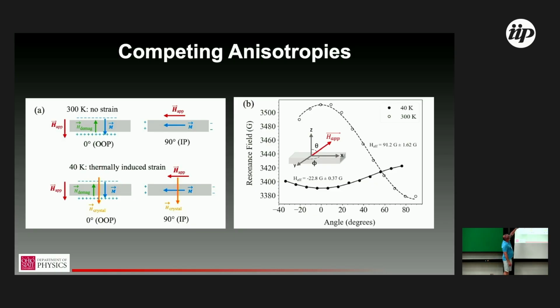And if we apply a magnetic field out of plane, then one way to think about the anisotropy is it generates a space charge, positive on the bottom, negative on the top, which gives an internal demagnetizing field oriented oppositely to your applied field. And so as you ramp your applied field up and down, you have the magnetization parallel to that, and you feel your total field is the applied plus the demagnetizing field. Then when you're in plane, that space charge moves to the edges of your film, so that the dipole there is negligible.